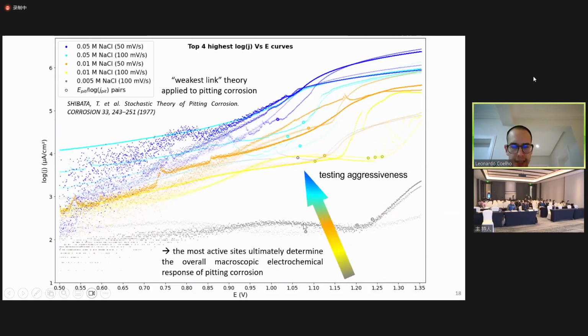And one last slide on this study. We have not yet attempted that, but we would suggest if somebody attempts prediction of pitting corrosion, instead of focusing on the entire population of curves, select the most active curves, because at the end, what governs the macroscopic behavior are these weak spots on the surface that are more susceptible to pitting, or at least to very intense pitting corrosion. So we will probably try it in the light of the weakest link theory, which, by the way, was already applied to corrosion research.